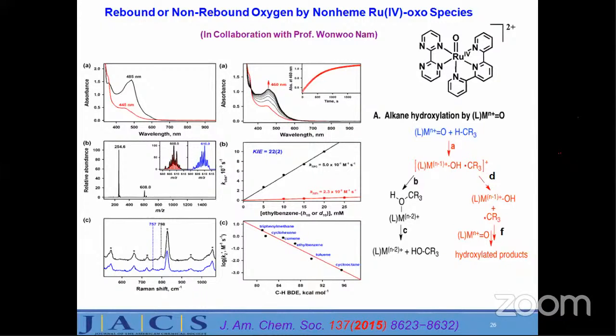Water oxidation reactions were reported, but they did not give clear-cut evidence for ruthenium 4 oxo with this ligand. That we have shown in our study, right? So you can see we generated the ruthenium 4 oxo species. The initial 485 nanometer peak is the ruthenium 2 species in acetonitrile, and on addition of PhIO, the absorbance of this peak decreases and it goes to something like 445 nanometers. There is a shift in the wavelength also, right?